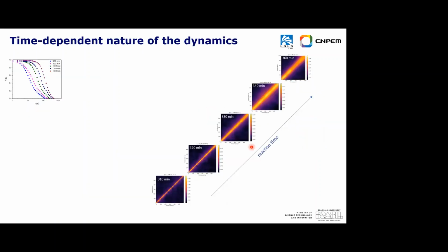So using this two-time correlation, we can get more information about aging, for example aging of the gel. Here we have the two-time correlation for the same system that I showed you before. Around 300 minutes you have this parallel line, because the system is still in equilibrium. Things are too fast. As the gel network is formed, it starts to slow down. We can observe the gradual slowing down of the dynamics, and the network fluctuations become greatly suppressed, and at some point we observe it increasing, and then at the end it seems to start becoming in equilibrium again.